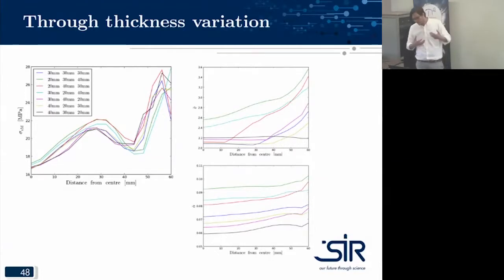In this specific case, perhaps once you've built a bit of intuition about it, because it's a logarithmic reduction, it would make sense to reduce it quite a bit to start off with, and then slightly less and slightly less. So the roll schedule that was 40 millimeters, then 30 millimeters, and then 20 millimeters is that black line. It's that fairly straight, fairly homogeneous line through the thickness you can see at the top. Versus the other extreme, doing 20, then 30, then 40 millimeters, is the green one at the top. So those are the two extremes.